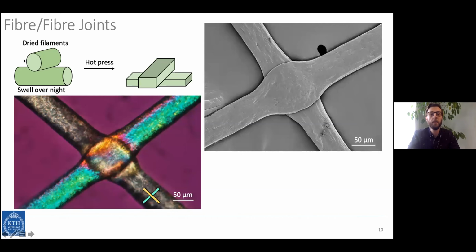We can dry the filaments together, or dry the filaments and then simply hot press them together to create these fiber joints. This is an example under polarized optical microscopy. We can see the aligned fibers going from the bottom left to the upper right, and oppositely in the other direction.